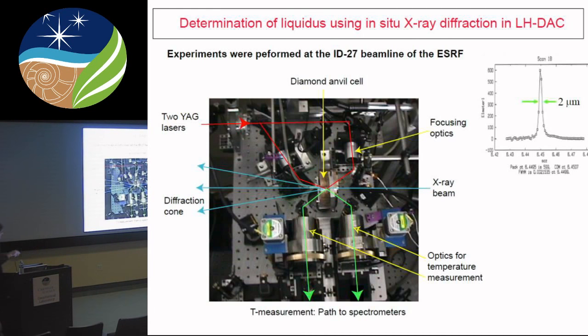So this is the system we use. These are the telescopes. This is the old picture, but it is easier to see what's happening than in the new ones, because we now use vertical lasers, but the picture is difficult to make. We don't see much. So these are the reflective objectives. They're usually pushed in, especially the one from the front, where the mirror is drilled, so you can keep the temperature measurements during the X-ray measurements. They're out at the moment, but they're pushed in. And at the back here, this is the diamond cell. The back temperature measurement is done only in between X-ray measurements, but the X-ray measurements last for 5 to 10 seconds, so it's not such a big problem. And the lasers are focused on the sample.